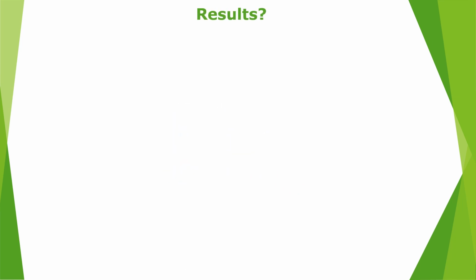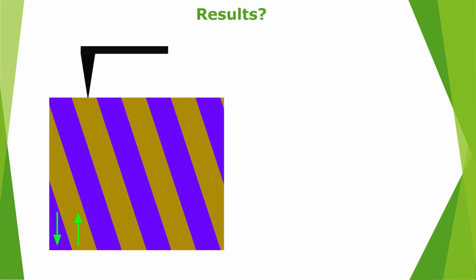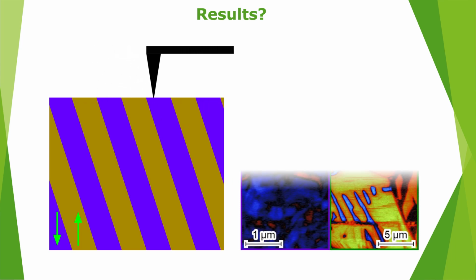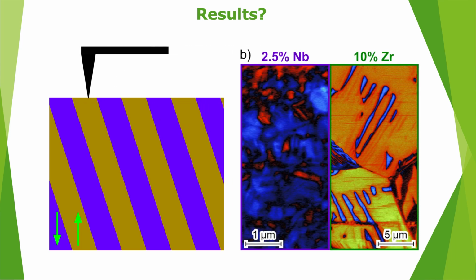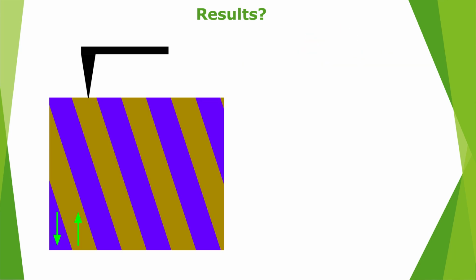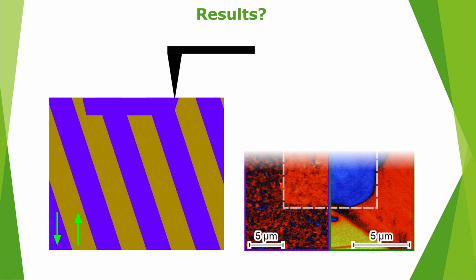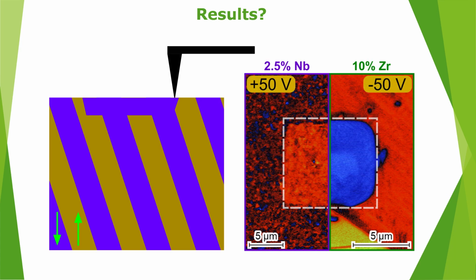Finally, what are the results obtained with this method? I used Piezoresponse force microscopy in three ways to attain information about these systems. First, I imaged a pristine domain structure by scanning the tip line by line on the surface, obtaining unique domain structures depending on the type and amount of foreign atoms introduced. Then, I switched the polarization locally by applying a voltage of up to 50 volts to the tip or sample, leading to local patterning of the domains.